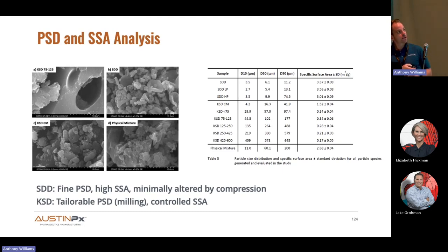And we also wanted to examine how you tune particle size for spray drying. Well, it's through compression. So we simulated high and low pressure compression, and you see the specific surface area doesn't really change very much. And likewise, KinetiSol particles can be tuned through the milling process, optimizing your milling parameters to achieve different particle size ranges. And within the typical range of particle size, we don't see the specific surface area change too much.